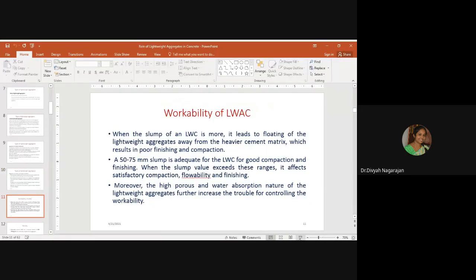Workability of lightweight aggregate concrete. This is a matter of concern when lightweight aggregates are used in concrete. The workability of lightweight aggregate concrete differs from normal weight aggregate concrete. When the slump of the lightweight concrete is more, it leads to floating of lightweight aggregates away from the heavier cement mix, which results in poor finishing and compaction.